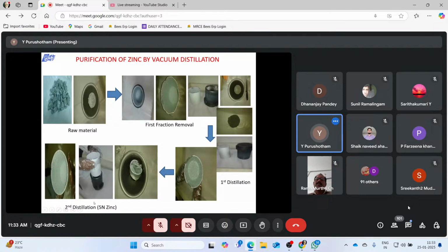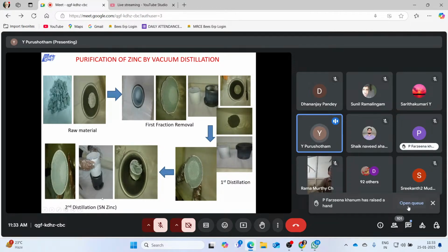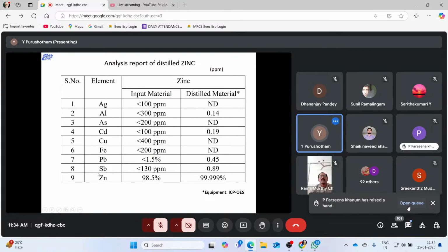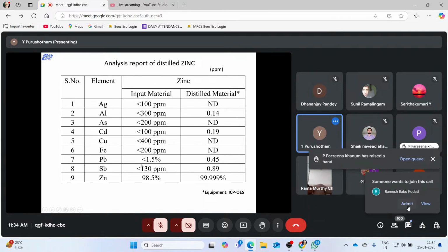So only zinc will come out, and from that we do further distillation, where you get zinc, and the surrounding high vapor pressure impurities will be removed, giving only zinc of 5N purity, 99.999. Here you can see the input material is 98.5%, whatever we purchased from the market, and this is the analysis report where other impurities are in ppm, but lead is 1.5 percent.